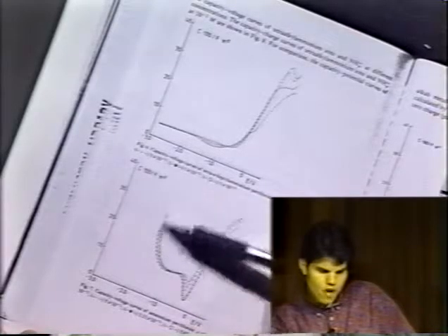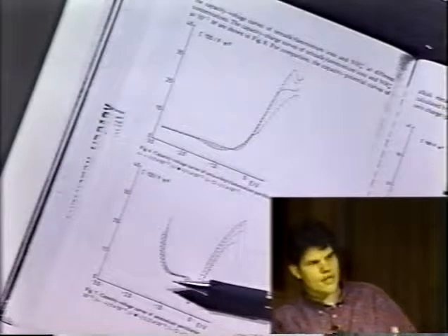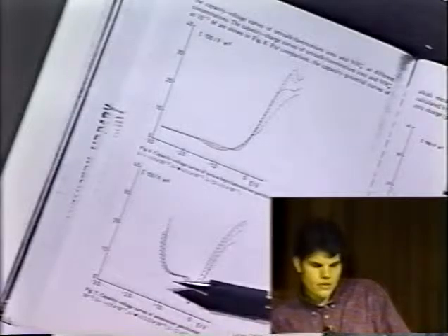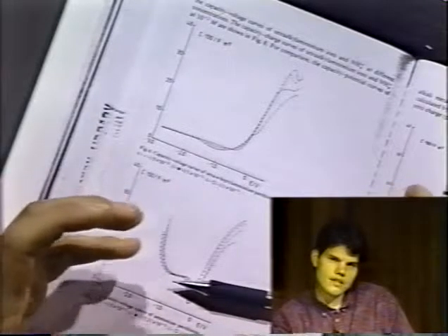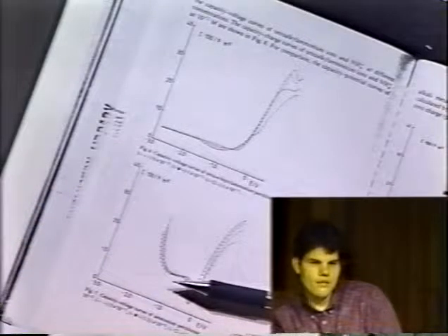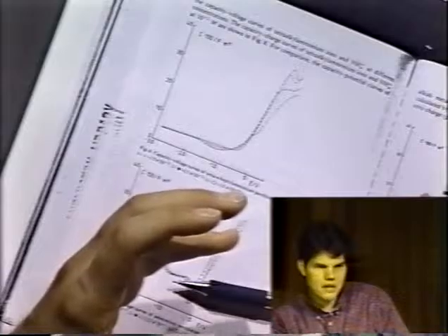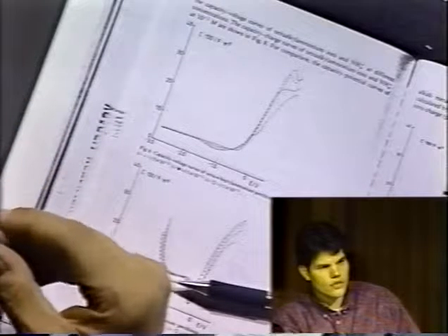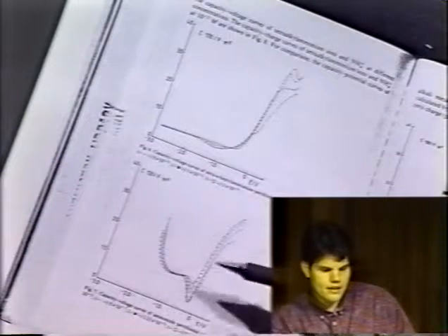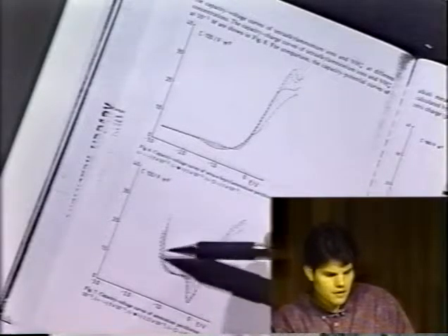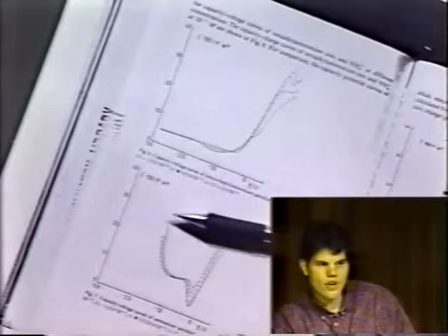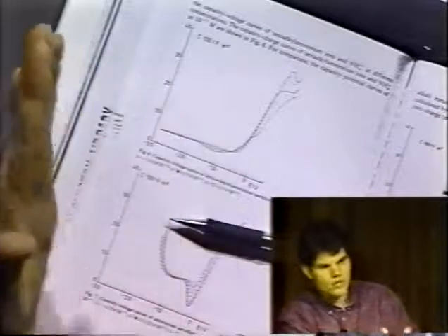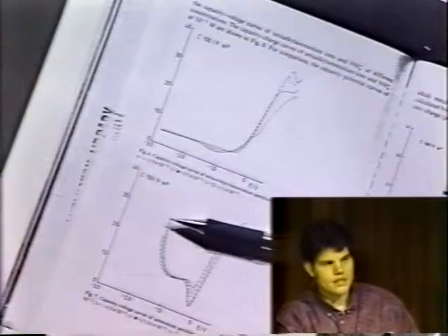But then we go to really small cations, and it picks up again, the ammonium perchlorate. So probably what's happening with the smaller ions is that we can have enough negative charge on that electrode to start to get specific adsorption of these cations onto the electrode surface. In other words, we're going from these ions being at the OHP to there being enough charge to really pull them right into the inner Helmholtz plane, so they're stuck to the electrode surface. In that case, you can see why the capacitance will increase dramatically. Now we've gone from a system where they're separated by the OHP to where they're separated by the IHP, so much closer to the surface. Now the separation is smaller, so we can get a higher capacitance.